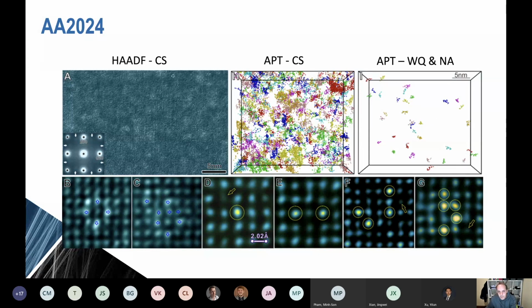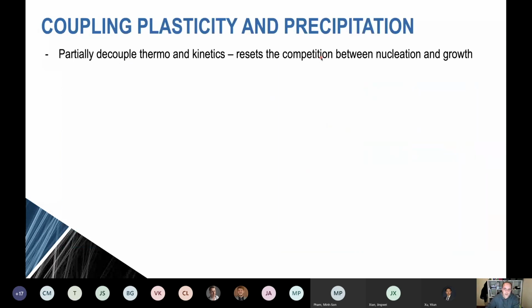And actually, by using some reasonable calculations of what we think is the strength of these clusters as shearing entities, we can rationalize pretty well the increase in strength. So these are really a cluster strengthened material. So this has come about from the coupling of plasticity and precipitation. And there's a number of what we find to be very interesting points about that.